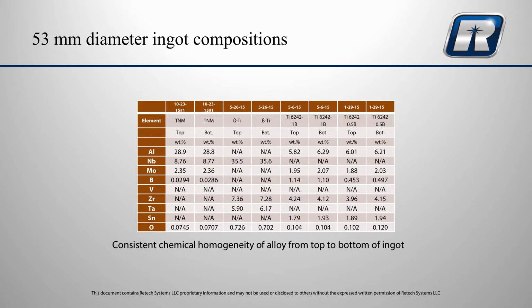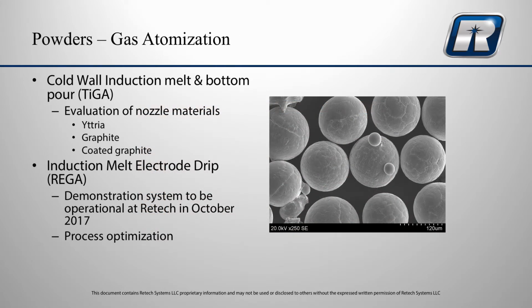Some of the other work that we've done with regard to the titanium aluminides has been in the area of gas atomization of powders. The traditional approach that we've been offering for many years, and are now able to offer as an equipment supplier because of the patent expiration, is the cold wall induction melt, what we're calling the TIGA. We've looked at evaluating different nozzle materials for that type of system, whether yttria, graphite, or even coated graphite for the titanium aluminides. We've also introduced what we call our REGA system, which is induction melt and electrode drip.